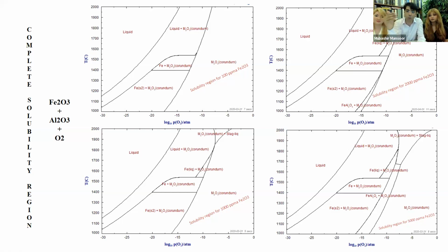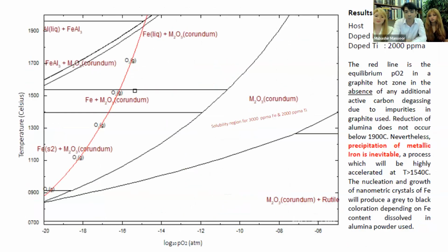Titanium requires low oxygen to dissolve, but iron is the opposite way. It requires too much oxygen to dissolve. So we should find the balance between the two. And that's the secret behind most of the successful heat treaters of blue sapphire. They know those perfect places to be. And these perfect places change based on your mine, because the concentration of iron and titanium changes as well. So you have to be careful with that.